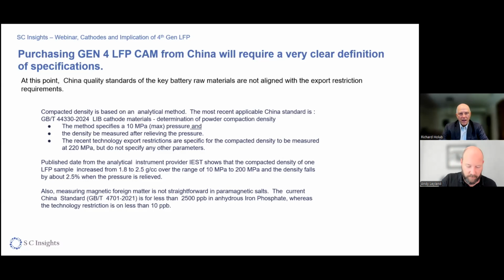And then the last bullet is around the magnetic foreign matter, which I mentioned much earlier. You saw the 10 parts per billion specification in the technology restrictions. But if you go to the GB standard around anhydrous iron phosphate, the actual standard lists 2,500 parts per billion, and also discusses how difficult it is to measure the magnetic metal material in a paramagnetic salt. So there's another example where you're going to have to dive very deeply into the methodology to set a specification if you want to buy iron phosphate from a China supplier. You're not going to be able to rely on the GB standards. With that, I'll wrap up. Turn back over to Andy to kind of close us out, I believe.